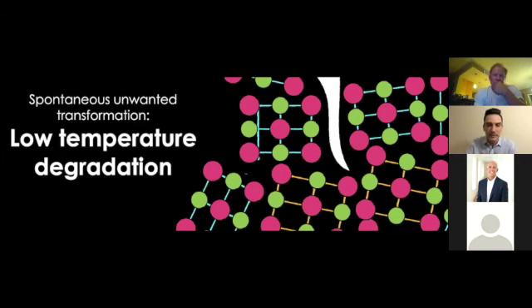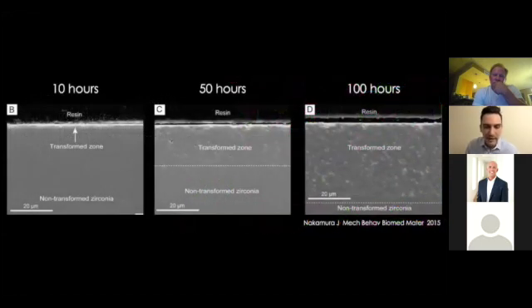But I mean, dental zirconia can undergo low temperature degradation. And again, they do these kinds of tests where they'll put it into an autoclave for various amounts of time, 10 hours or 50 hours. They can show from the surface of the zirconia that you would start to see some of these grains separate because they're transforming and there are cracks in between them. And you leave it in there longer, 100 hours in the autoclave, and you can see a transformation zone of probably somewhere around 60 microns from the surface of the zirconia.